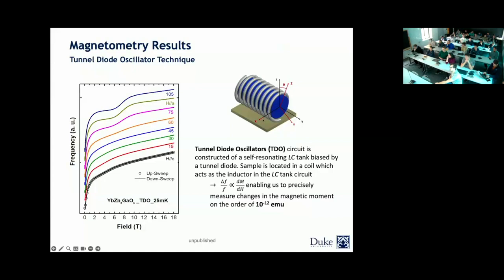So here I'm showing you the data. That's the frequency and this is the field. When we are at zero, at H parallel to a, or perpendicular to c, you see there is this nice plateau that shows up. When we start to go away from it toward H parallel to c, it starts to diminish and move down in field. This is in agreement with what we saw in our SQUID measurements as well.